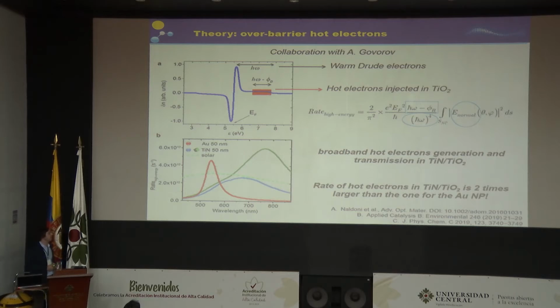So here is the rate of high energy electrons which really makes it into the semiconductor, considering the experimental values of the barriers. And as we can see here, the rate of high energy electrons which goes to the other side, into the semiconductor, is much higher. So you can see that if you integrate this contribution of titanium nitride versus gold, we have like 2 times higher hot electrons which go to the semiconductor. So this doesn't really fit with the 25% increase that we saw in the photocurrent, but okay, this is a theory, and there are so many other different parameters to take into account to really estimate precisely how many electrons go from the metals to the semiconductor.